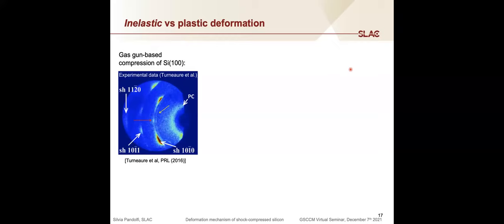And in particular, it's very interesting to compare with this gas gun based study of single crystalline silicon 100 compression performed by Turneaure and co-workers and published in PRL in 2016. In this case, the authors have proposed a specific orientation relationship that we have tested and cannot explain our data. So it suggests that there must be some differences between what's happening in this experiment and in our experiment.